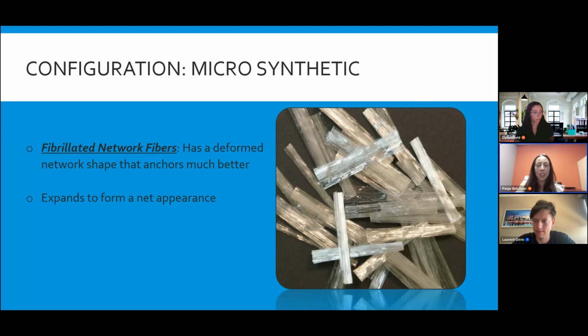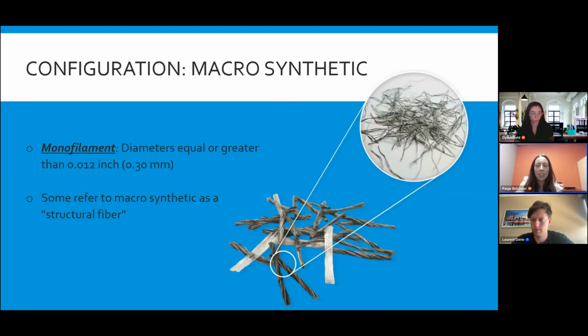But where we definitely want to talk a little bit more about, and things get a bit more exciting and we can set ourselves apart better with our macrosynthetic option. So this is our bread and butter, known as a structural fiber. This can be used to replace essentially all mesh, including heavier duty mesh, and for that being temperature and shrinkage. And the macro can also replace lighter duty rebar as well. So of course, that will depend on the exact bar spacing and sizing, but whether it's a single layer replacement or a double layer, we're going to be dosing these anywhere from 3 pounds to 7.5 pounds on slab on grade, pavements, slab on metal deck.